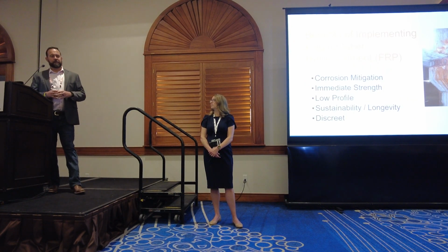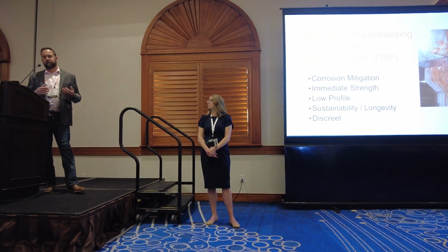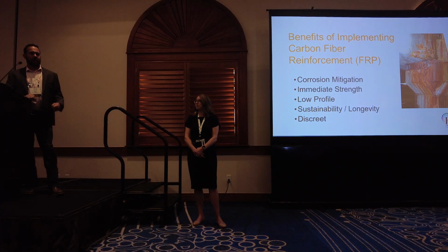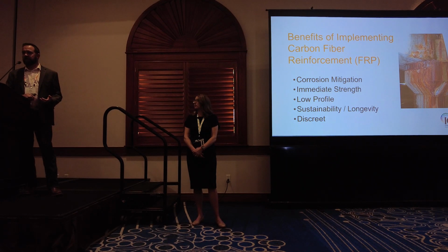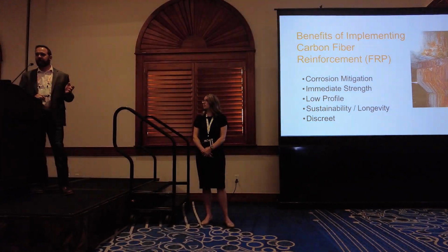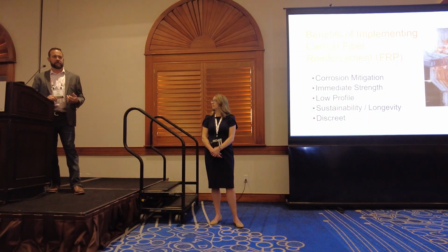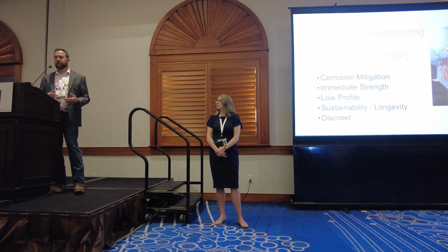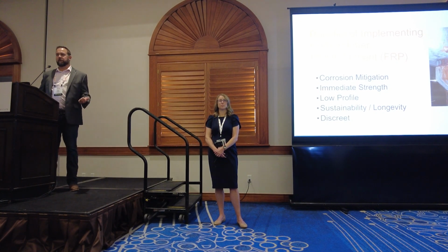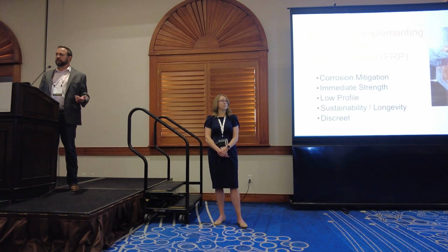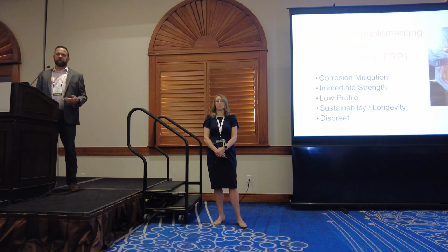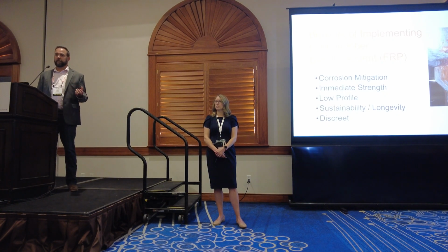So there are other benefits to the fiber reinforcement, and one of them that is really important is the corrosion mitigation that it can offer in certain applications. We've tested a lot of the epoxies over the years to see what the reduction in corrosion is, and then as Tami pointed out earlier, they're doing wraps, not full wraps, but smaller wraps to allow moisture to escape the system. But in column applications, you can really prevent a lot of chemical intrusion from getting in. Another benefit is the immediate strength. Whereas traditionally we would need to wait 7 to 28 days to get our breaks back, depending on how they come back, to get the scaffolding or shoring out of the facility, with fiber reinforcement we can traditionally get all of that shoring out within 7 days.